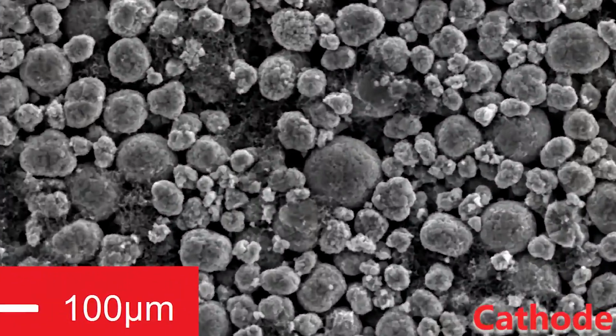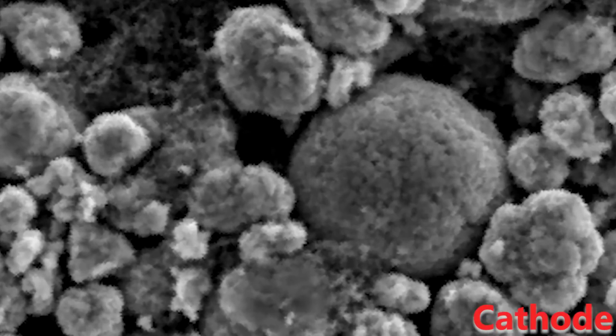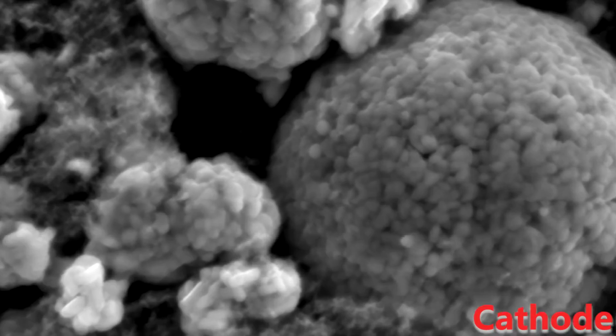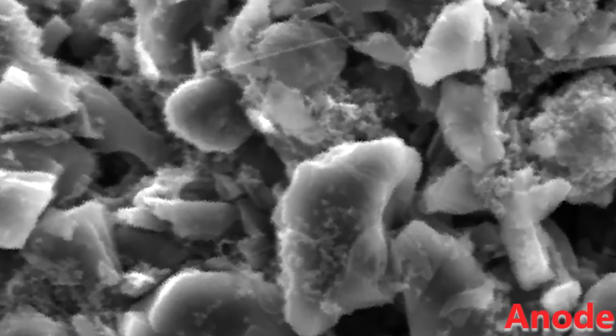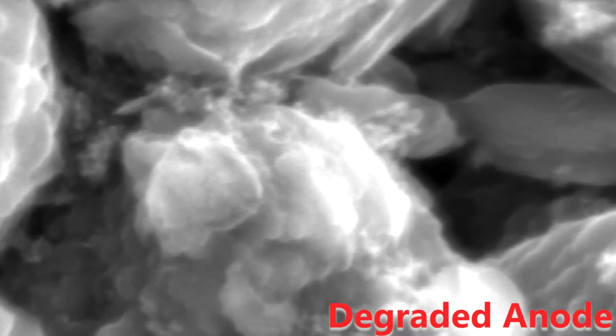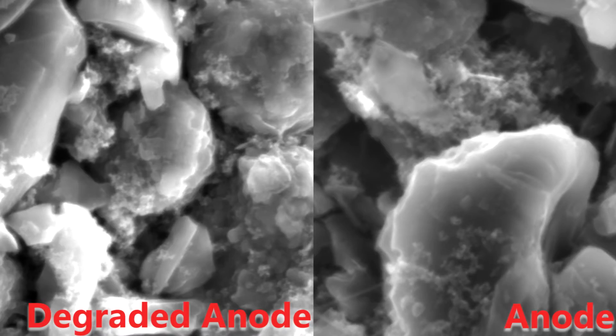The cathodes show different sized NMC particles. It's also possible to see the binder between the particles. It's noted that there is no change between the fresh and degraded cell. With the anode cells, the graphite particles are clearly seen. The surface is relatively smooth and parts of binder and separator can be seen. With the degraded cell, the surface is clearly more broken, which is likely due to the pore formation of the SEI. And comparing the two, it's reasonably obvious which cell is degraded.